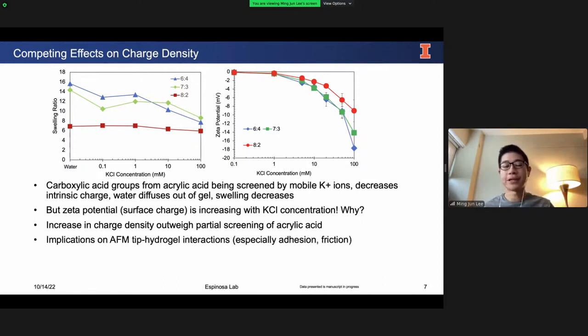This has implications on the interactions between the AFM tip, which is the method I'm using to measure these hydrogels, as well as the hydrogel surface. And this would especially affect the adhesion and friction data that we see in the previous and also the following slides to come. Now I'd like to move on to the friction experiments using different concentrations of salt solution. And what I'm showing here, on the first row, is the height channel of the quantitative images that I showed earlier.